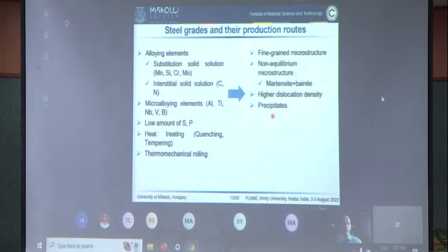With these technologies, a very fine-grained microstructure can be achieved, which is generally a non-equilibrium microstructure with the combination of martensite and bainite, but different kinds of carbides, retained austenite, and in some cases ferrite can also be identified in these high-strength steels. Some measurements have shown that there is also a higher dislocation density in the material, which also results in higher strength, and there are precipitates thanks to the precipitation hardening alloying elements such as chromium or molybdenum, which can be considered as carbide former elements.